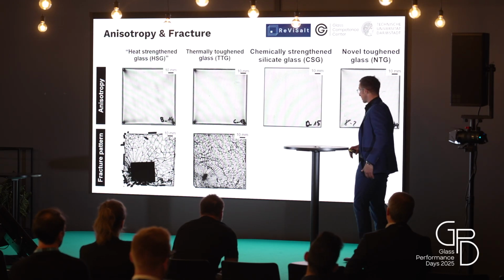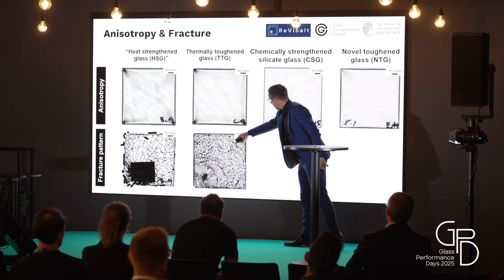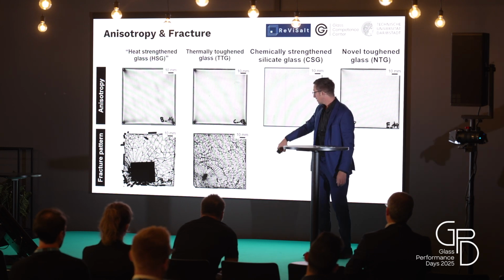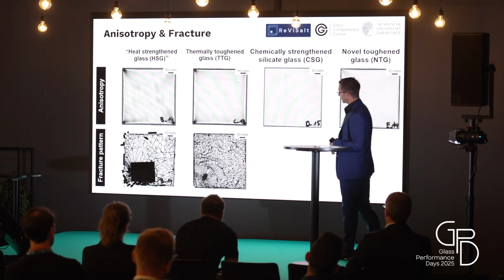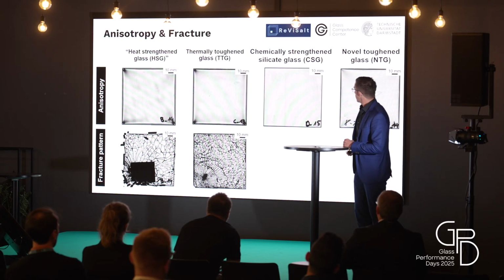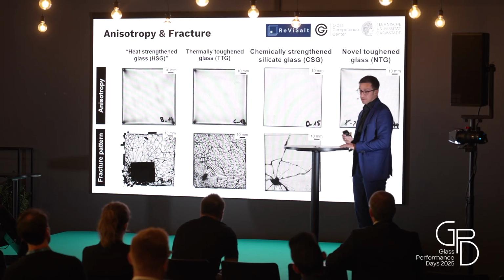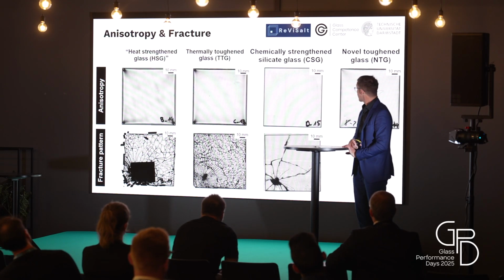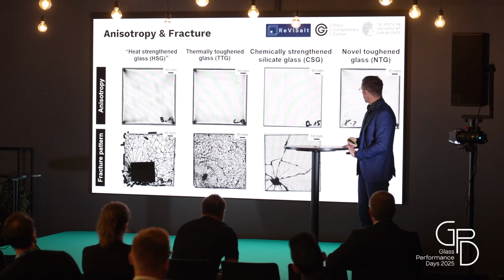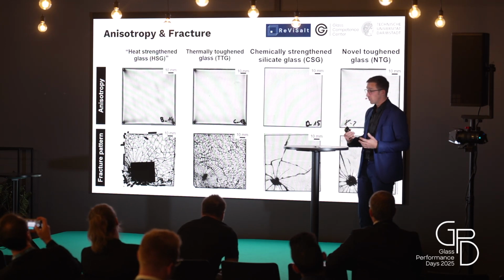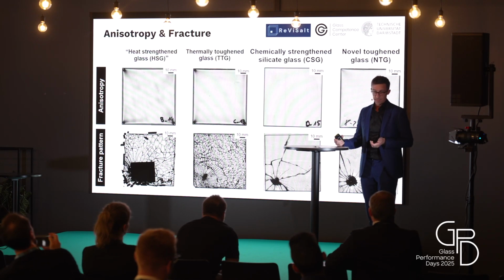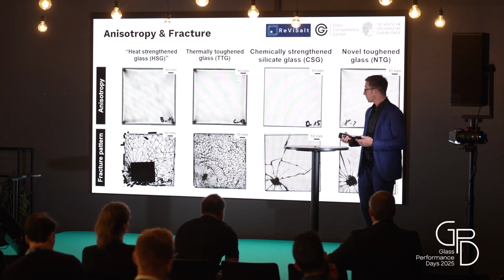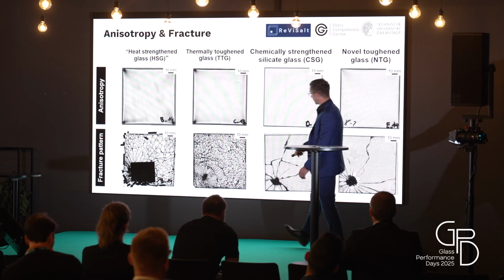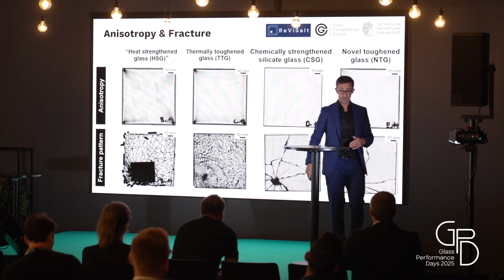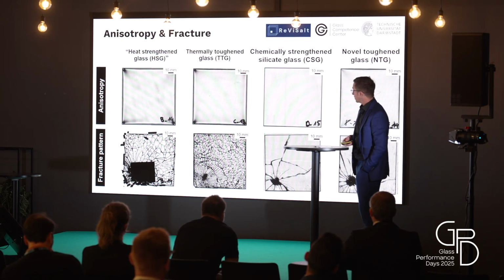These are the typical fracture patterns. These are here 1 centimeter. The fracture pattern for the heat strengthened glass, it's too much, I know. This is the normal fracture pattern for the chemically strengthened glass, and it's more or less the same also for the novel toughened glass. And this is pretty helpful for the post-breakage behavior. I don't want to build with this glass, laminated safety glass, as an overhead glass.